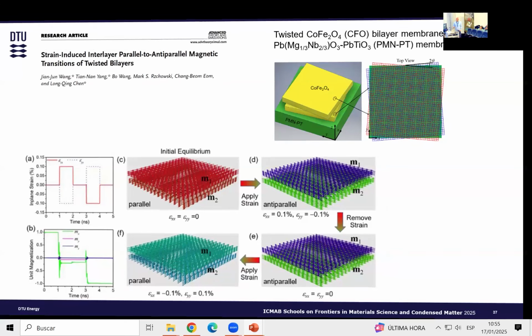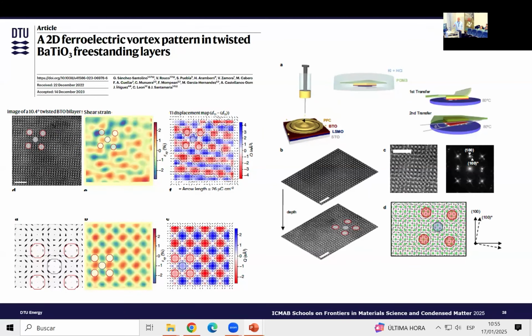We know also there is something about how the twist of membranes can bring about some properties. This is the work of Jacobo, and I don't think I will say more than what he says because you have seen it before. So here you can put 2 layers of barium titanate, rotate them, and you can see some vortex, which is a ferroelectric vortex. I think most of you have seen it before and heard the talk of Jacobo, but this is another experiment where, in my opinion, it's the first experiment where someone took the 2 layers and saw this effect at the interface, where we can see some influence of the rotation at the interface.